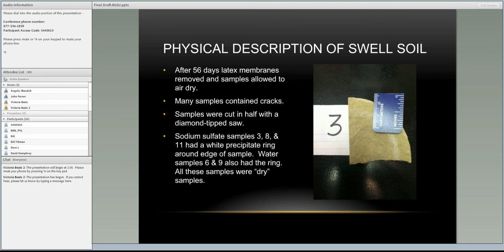So a summary of Objective 3. We wanted to replicate soil swelling using the material from Lake County Route 2. And what we found is that some of the high sulfate concentrations didn't necessarily indicate the largest SWELL performers in our SWELL samples. We feel this is largely due to the heterogeneous distribution of sulfates in the soil, primarily gypsum in the case of Lake County. However, the soils that did swell a lot in our SWELL test were well above 3,000 parts per million. So we still feel like 3,000 parts per million is a good limit to set on your sulfate values.